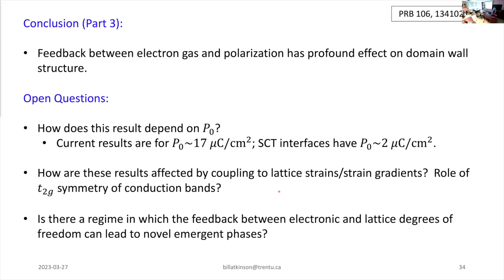Strontium titanate is somewhat special in that the vast majority, well over 90%, probably well over 95%, of the dielectric response comes from a single phonon mode. All the other phonon modes are there, but they're kind of irrelevant. And then the electrons, they're all in d states. Right. And what's your filling?